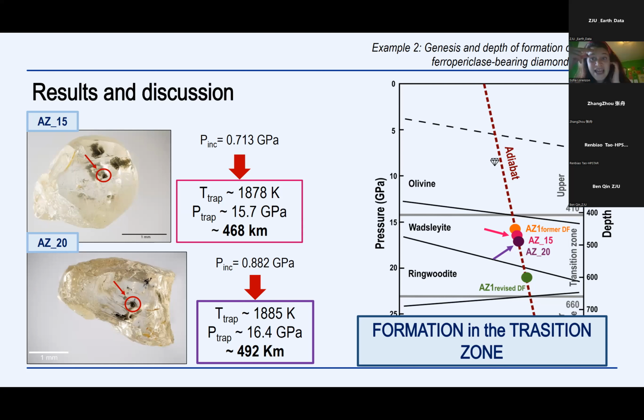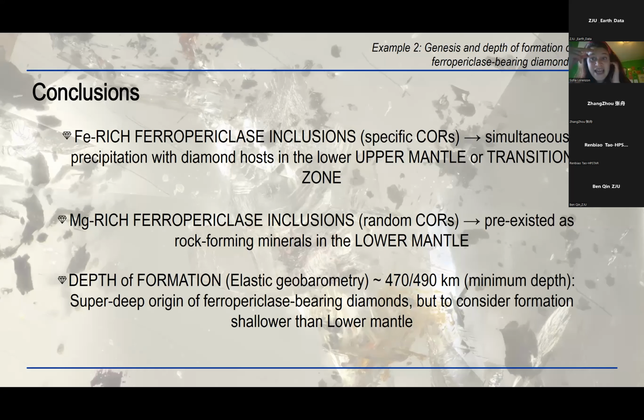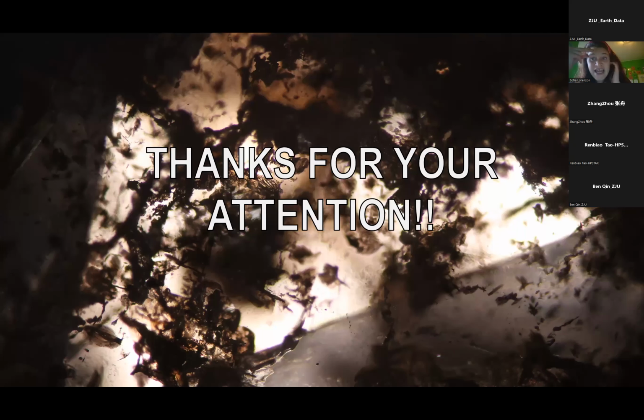So in conclusion, from the study of the ferropericlase-bearing diamonds, we obtain that ferropericlase inclusions with different chemistry have different origins as a function of their iron-rich or magnesium-rich nature. And we also obtain that this information is supported by the elastic geobarometry, where we obtain that ferropericlase-bearing diamonds can also form at shallower depth with respect to the lower mantle. So this is the last slide. I want to thank you again for the attention. And if you have questions, I'm ready to respond.